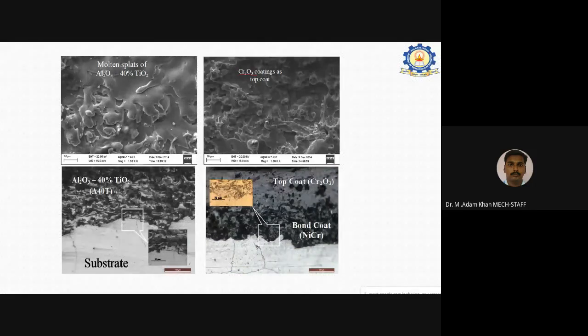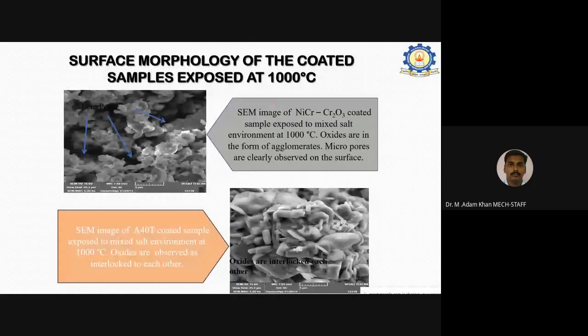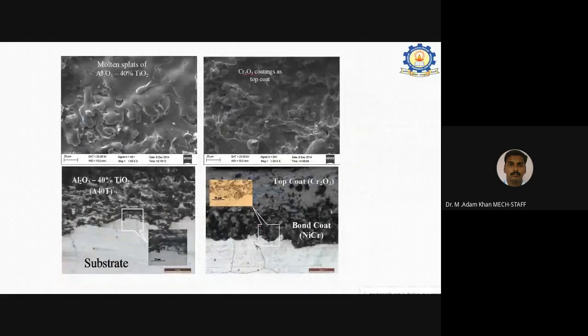So when it is exposed at 1000 degrees centigrade, you can see these oxides are in the form of agglomerates. Okay, micropores are very clear. And this is for alumina titania. See how this coating has turned like this.